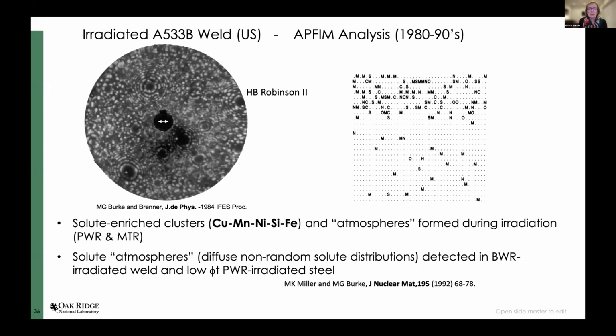For those of you that might not know, this is a truly atomic resolution image. This is a field ion micrograph, and this happens to be of a body-centered cubic ferritic weld. This was from a surveillance sample from H.B. Robinson 2. But we can see our main crystallographic poles. Atom probe specimens are needles. You probably are aware of that. But field ion microscopy was a very impressive technique. And this very tiny arrow that you see represents the entire diameter of the entrance aperture to the time of flight mass spectrometer. So most of those field evaporated ions were wasted, unlike today with atom probe tomography, where you can collect all of them.